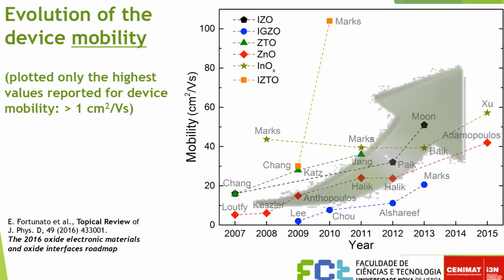And if we plot the same devices, but instead of the final deposition temperature we plot the mobility, this figure of merit, what you observe is that as the years go on, and as we refine the technology, we have an increase in electrical mobility. So we are decreasing the temperature of the process, starting from solutions, and simultaneously we are increasing the mobility, which is quite good. In some cases it is questionable, but it is possible to achieve values around 100 square centimeter per volt per second. And if you compare these values with amorphous silicon, the one that we are using in our displays, the mobility is 1, and they are using CVD and toxic gases.